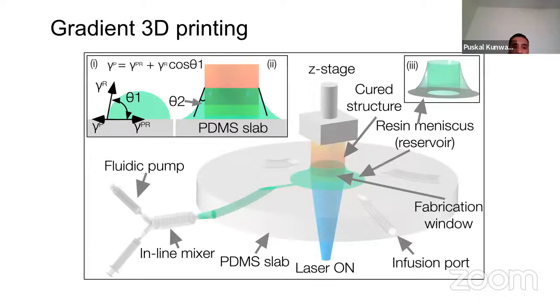Now in MAPS, one of the main advantages is gradient 3D printing. Just the concept of that meniscus again. Let's say this gray region is your PDMS slab. If you drop a resin, based on your contact angle it is going to make a dome-shaped structure. This is defined by a contact angle θ1. In our case, with our resin, θ1 was mostly 75 to 95 degrees.